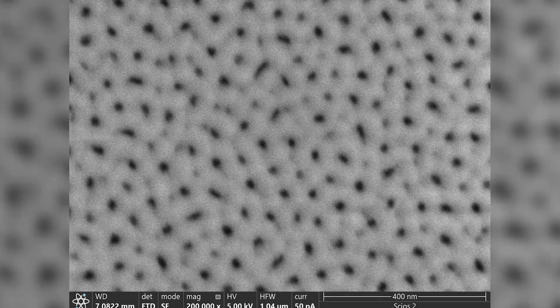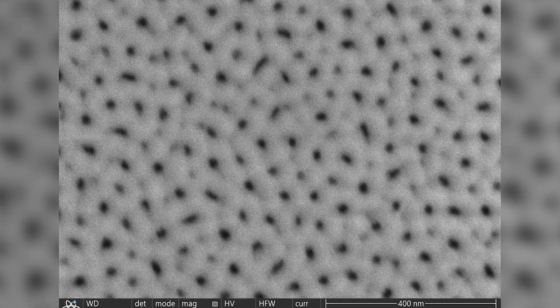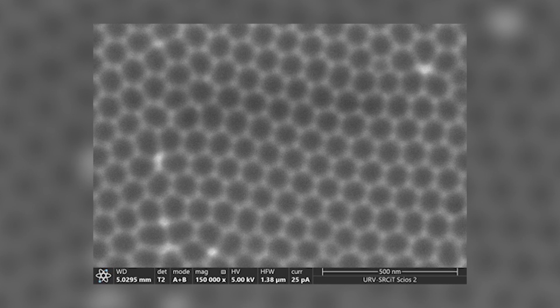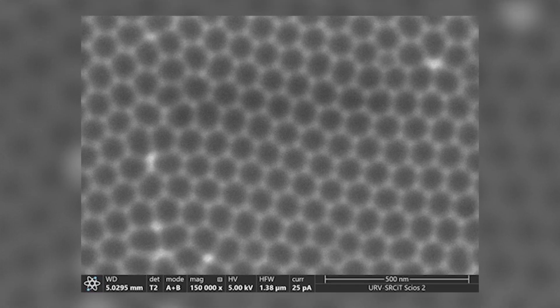Even so, what we have just described produces disordered pores — there is no specific order in what we have seen. The pores are literally formed where the fissures occur in the aluminum oxide. However, scientists Masuda and Fukuda developed a two-stage method that managed to turn this type of structure into something perfectly ordered. They developed what is known as soft anodizing, which basically involves performing the procedure described earlier, but then applying a treatment to remove the aluminum oxide, leaving only the gaps previously created in the metal by the oxide formation. After that, the anodizing process is repeated on that surface, resulting in much more ordered structures than before.